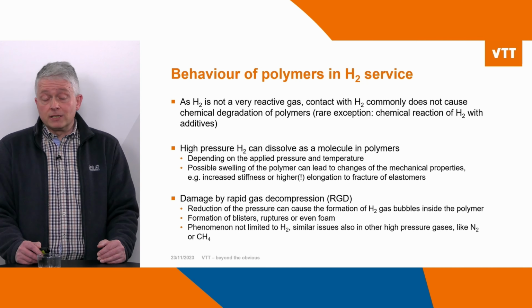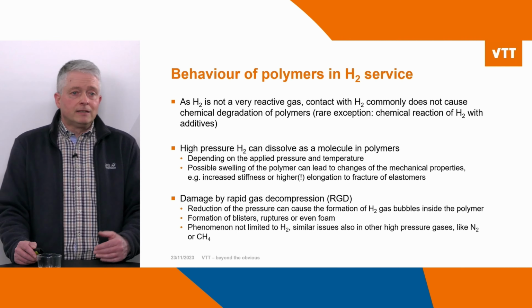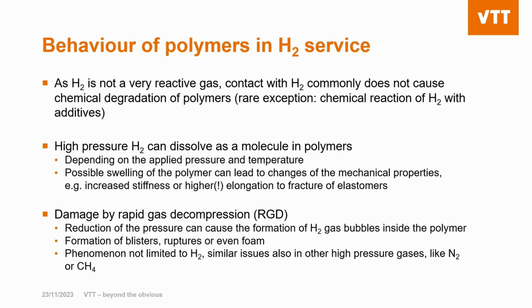When you look at polymers, the situation is a little bit different. Hydrogen is interacting differently with polymers. It is actually not a very reactive gas and does not cause direct chemical degradation of a polymer. It may sometimes react with certain additives, but this is a really rare case. It's usually dissolved in the polymer as hydrogen molecules, and especially under high pressure, this can lead to swelling of the polymer, which then changes its mechanical properties. For instance, the stiffness of the polymer can increase, or the elongation of elastomers will become even higher when there's hydrogen pressure from the outside.